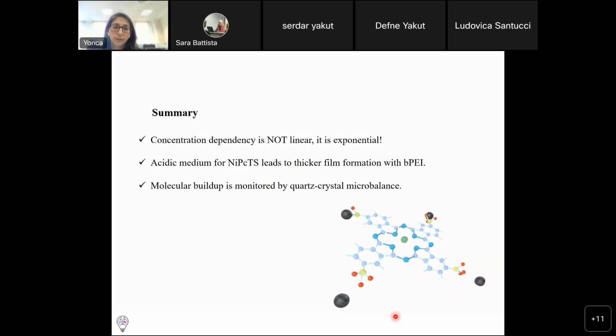Also, once you have an acidic medium, you have thicker films. And it's possible to control the thickness of the material by changing the acidic medium of the deposition solution. And you can monitor in real time the molecular buildup by quartz crystal microbalance.